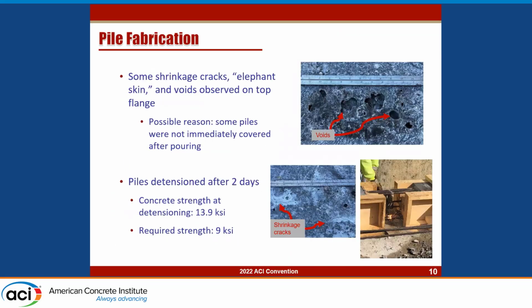So we did notice some shrinkage cracks, voids, and what we call a rough elephant skin on the UHPC after a day. You can see some of the larger voids that we saw, as well as some of the shrinkage cracks right there and right there. We suspect that this was because some of the piles were not immediately covered after pouring. We waited for all of the piles to be poured before we covered any of them. So some of the drying shrinkage could be because of that. But after 2 days, we checked the strength. We needed at least 9 KSI of strength, and we got 13.9 KSI at that time. So we went ahead and detensioned.